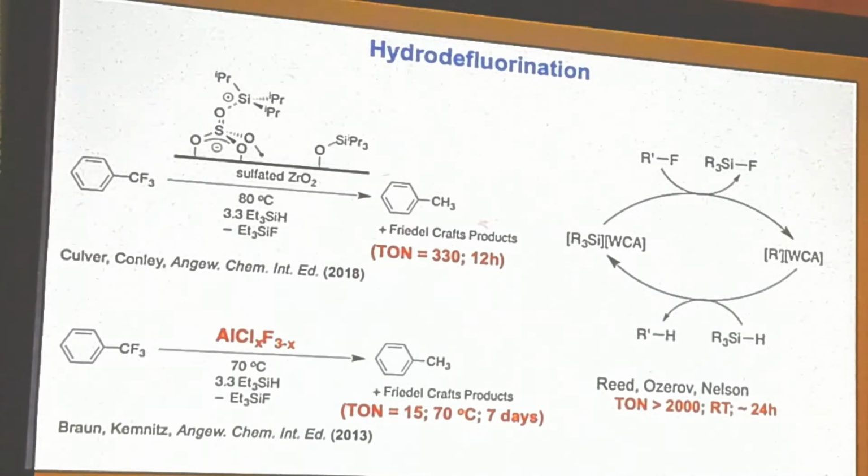There's modest activity. If you compare it to the state-of-the-art weakly coordinating anions, so these are typically carborane anions that were looked at by Chris Reed and Oleg Ozerov, and lately by Hosea Nelson, you have much higher activities in hydrodefluorination. This was the most active heterogeneous species for hydrodefluorination chemistry. So we know that we have something that really is behaving like a silylium ion. Okay.